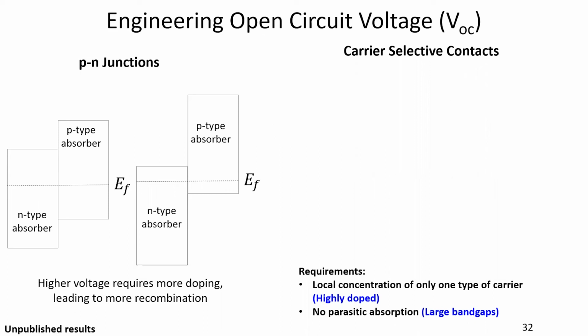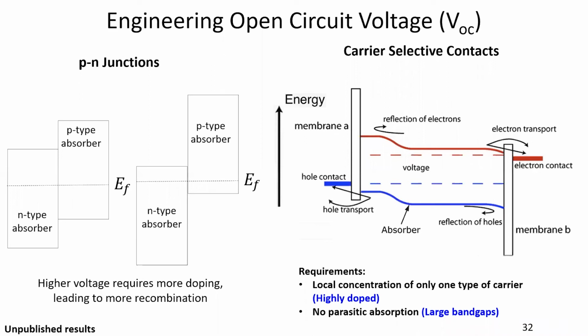And so the real way to go about this is the use of carrier selective contacts, and this is something that the silicon people have done really well, where you use a nearly intrinsic absorbing layer, and then you have wider band gap materials which are heavily doped, such as conducting oxides, for example, where one edge of an n-type conducting oxide is aligned with the conduction band of silicon, and the other, the valence band of a p-type conducting oxide or any other wider gap conducting material, is aligned to the holes. In that case, if your material is thin enough, your excitons or carriers are always going to reach a contact and get separated there, and the other carrier won't be able to recombine over here, and instead would get pushed back to the other contact where it will get collected.